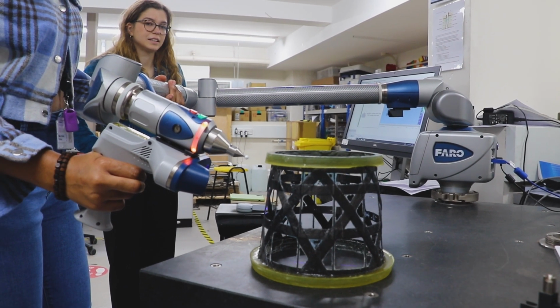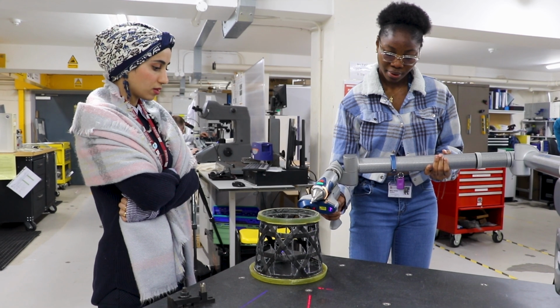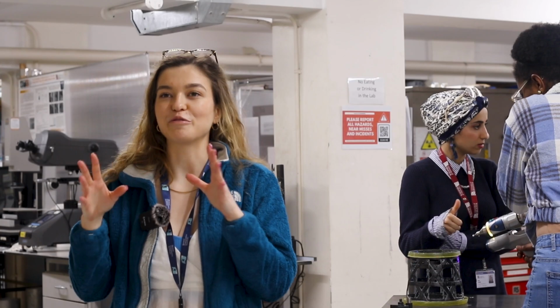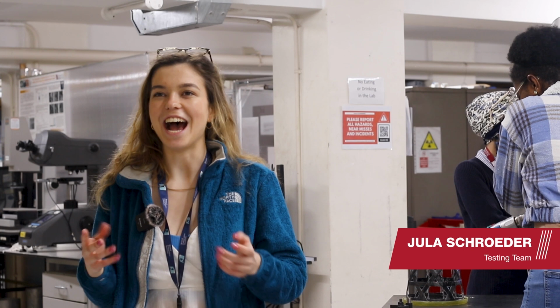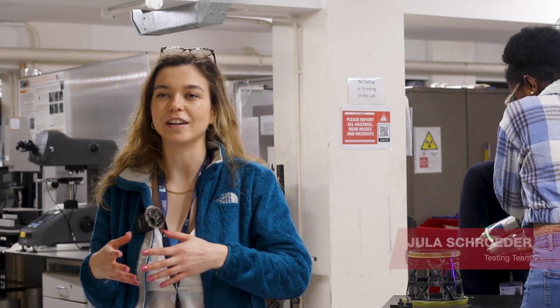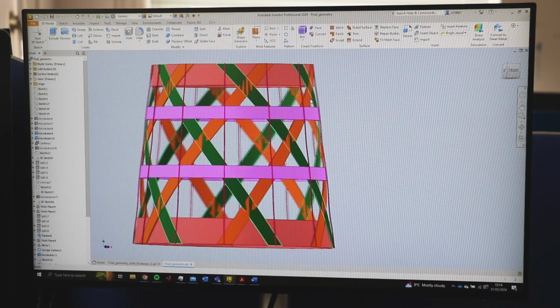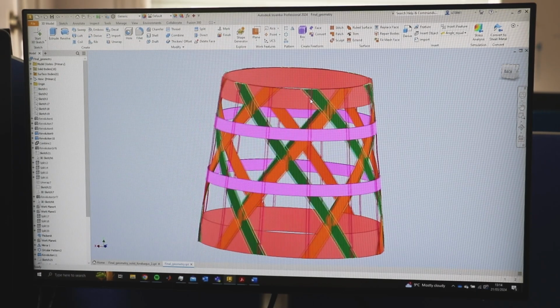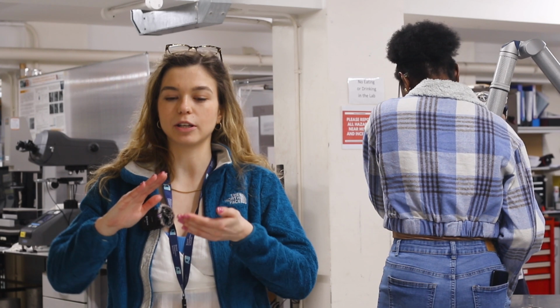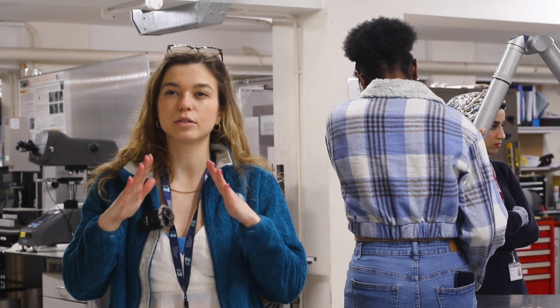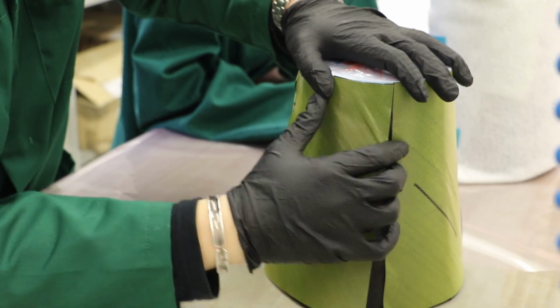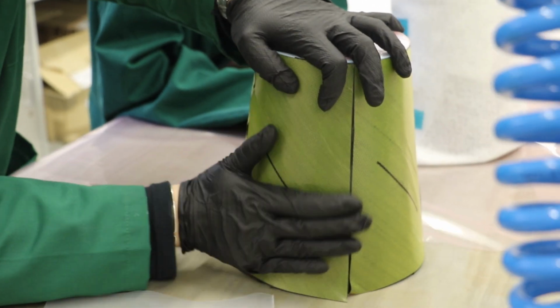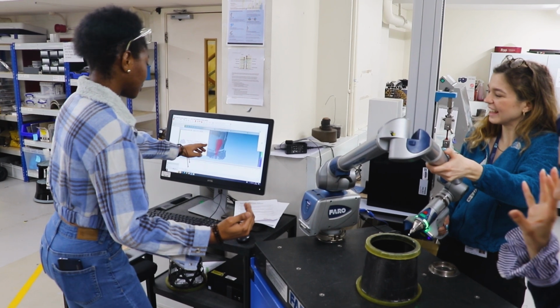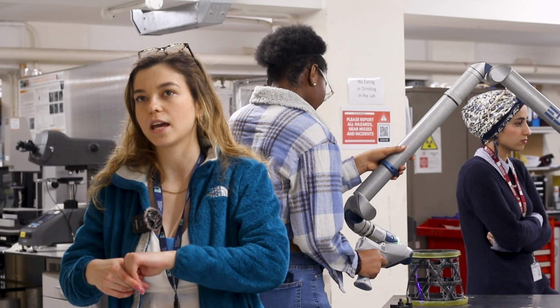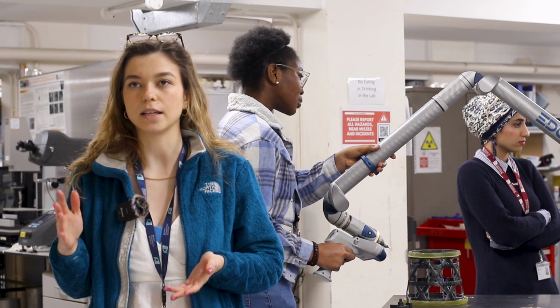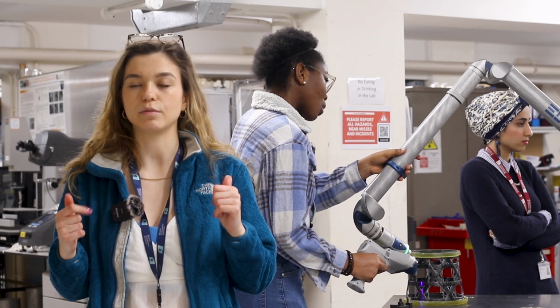So today we're doing some laser scanning with the FARO arm, 3D scanning our samples. A lot of the time when manufacturing, it doesn't always go perfectly. And the FEA analysis that we have currently is obviously very perfect in Abaqus. So now we're trying to see what the reality of this actually is. With some of the baseline cones, because it's just ply, we have a lot of wrinkles that happen during the manufacturing. So with that laser scanning, we hope to pick up on the imperfections and the wrinkles, especially along the lines, and then feed them back into the FEA, doing the FEA compression testing with the new STL files that we get from the laser scanner.